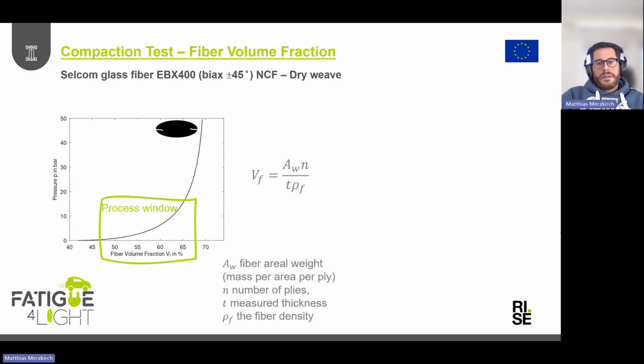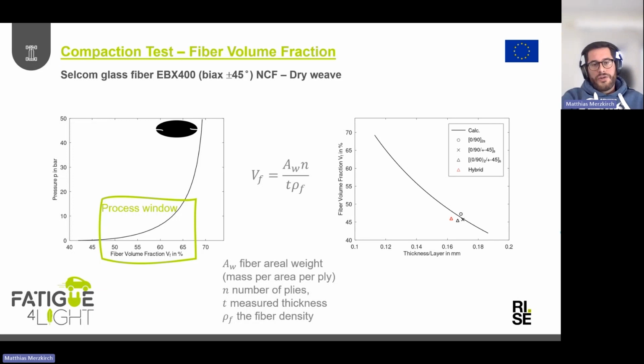So what did we do here? Different layups were tested or manufactured. Here on the right side, you see the calculation. It's basically, the thinner the material, the higher the volume fraction. And here are a bunch of measurements that have been determined via a burn off, so that only the fibers remain. That means this calculation is based on the dry weave. Those are materials where we already have a composite, so we're adding some polymer resin to that. Porosity has been excluded, but you see overall as a rule of thumb that we are in the range of 45% volume fraction and a layer thickness of roughly 170 microns of a single layer in this case.